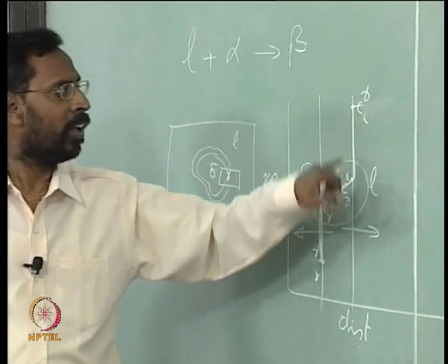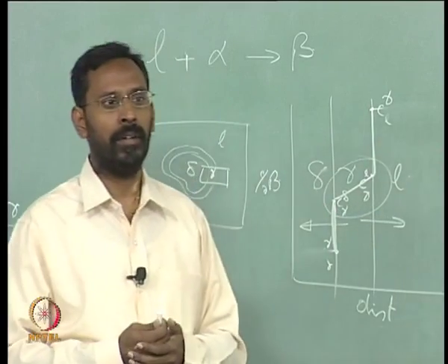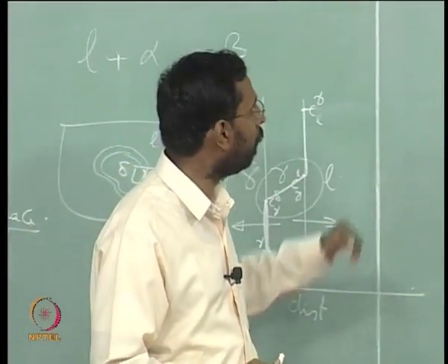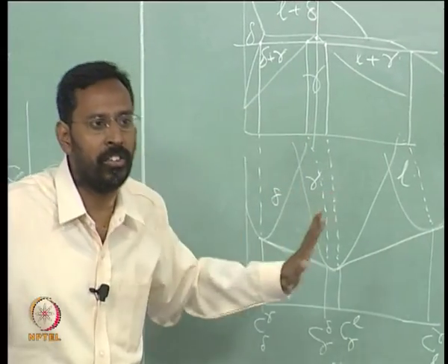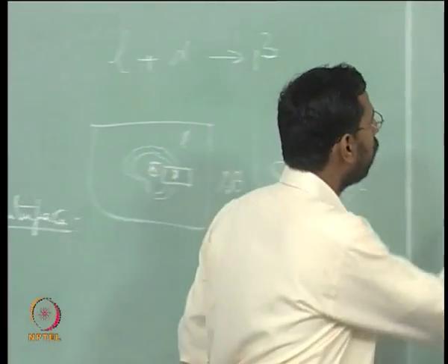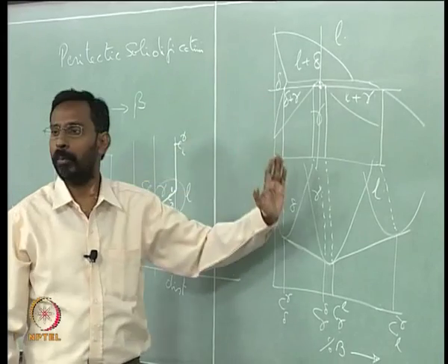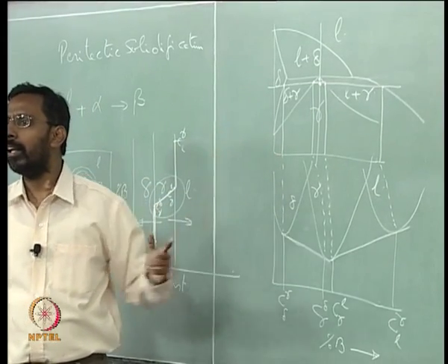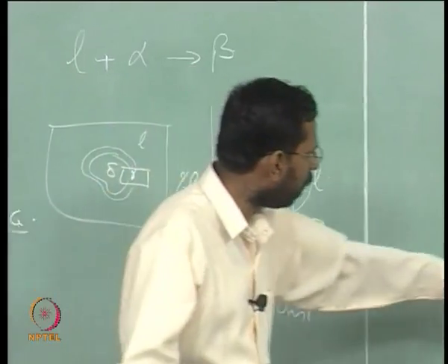So, in order for the peritectic transformation to complete, because why does this have to happen? Because at that temperature, for that alloy composition, liquid is not stable, is it not? If I am at this temperature, for that alloy composition with which I have started, what is stable is only gamma thermodynamically, that I can clearly see here.